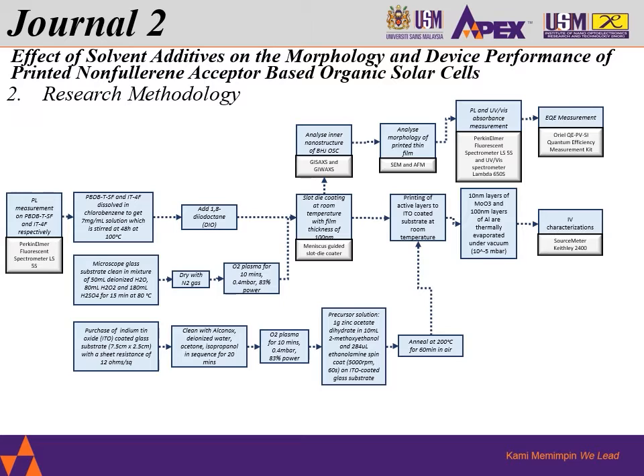So after that, before proceeding to the printing of this active layer onto the substrate at room temperature, the substrate was first purchased and also prepared beforehand. So over here, indium tin oxide ITO coated glass substrates were purchased, and then cleaned with Alconox, deionized water, acetone, isopropanol, and then going for O2 plasma, then going for the precursor solution, which has been coated on this substrate and annealed at 200 degrees Celsius. So then it is ready for the active layer printing on the substrate itself.